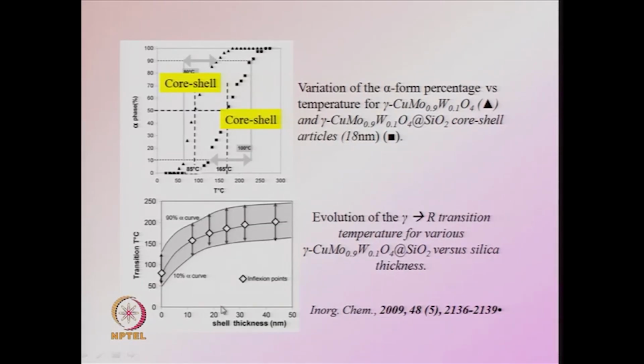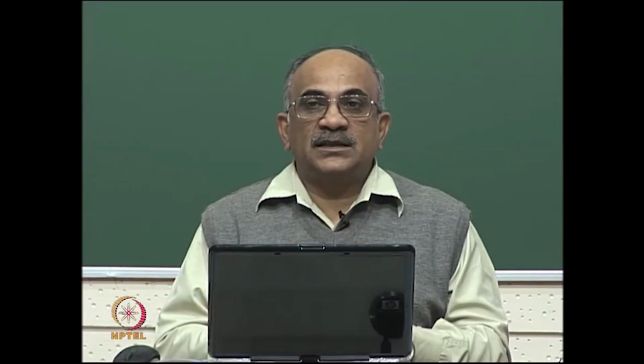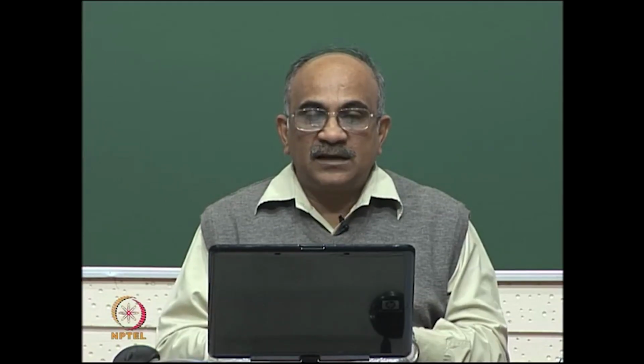So, what you learn from this is that if you make a shell on top of the core, the stability of the core has been enhanced by the shell, and the core transforms at a much higher temperature than it would if it did not have the shell.